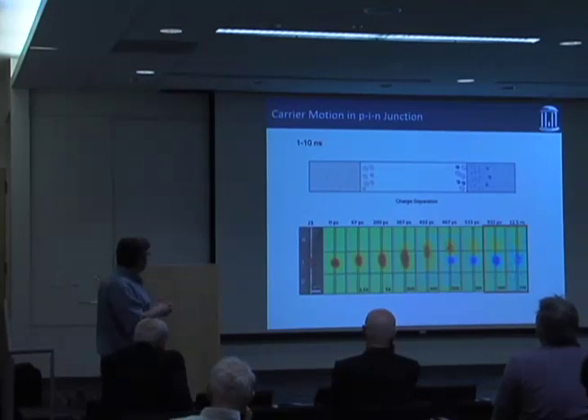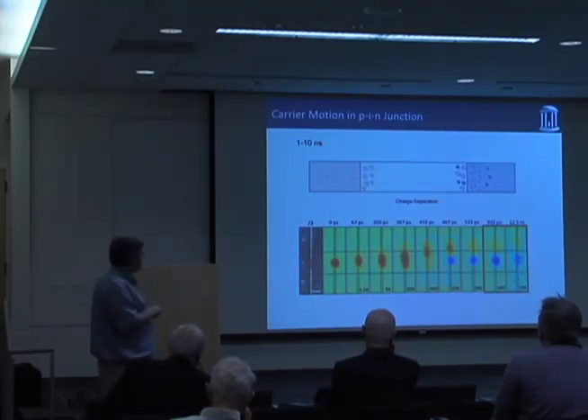This could be that in the transient absorption experiment we're just not sensitive to the holes. That's one possibility. Another possibility is that maybe the holes get spread out over a much larger section of the nanowire, and so their density is too low to observe.